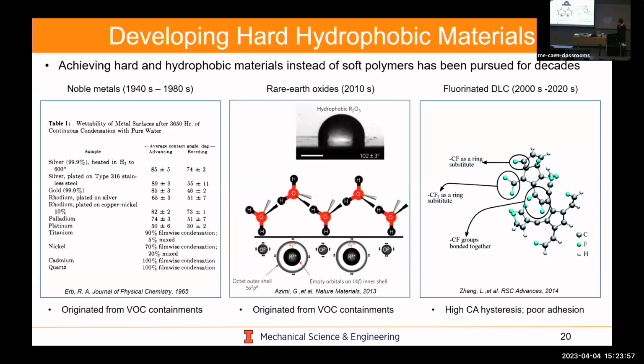The other approach that I'll tell you about is tailoring the material's intrinsic properties. So you could either get rid of pinholes, which some can argue you'll never get rid of all pinholes. But given that we know how wet adhesion and Young's modulus affect durability, can we actually make materials that have a high enough Young's modulus and high enough wet adhesion to give us the properties that we want for stable hydrophobicity? And so the one thing we looked at was diamond-like carbon, right?